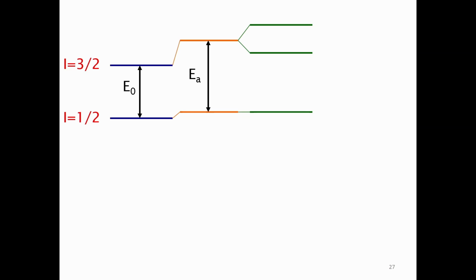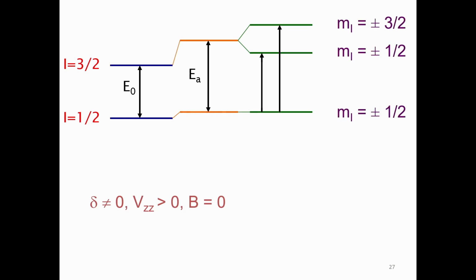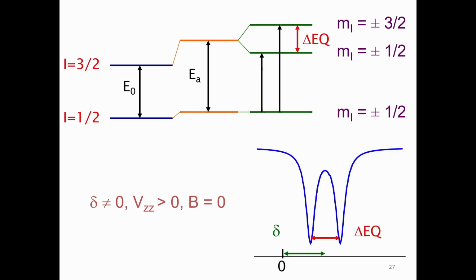Okay? So, at the difference of the first hyperfine electric interaction, now you will split your excited level. But note that the fundamental level is not split, because you may have -1/2, +1/2, and so on. So that means you have a partial degeneration. And what happens? You have to apply selection rules, and at the end, you will obtain the possibility to have two transitions, with such states. And finally, between the two sublevels, you will obtain a doublet.